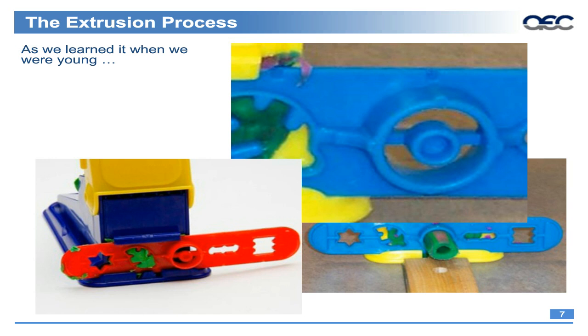when the billet is forced through the die itself, the die is fixed with a mandrel in the middle, and then you would have the bracing for the mandrel on either side of the larger opening. The billet itself, once it's forced through that opening, is actually broken into two separate or sometimes multiple pieces. And then as it flows back through the larger opening, is basically welded back together and forms the tube as you would see it in the lower right-hand corner of the screen.